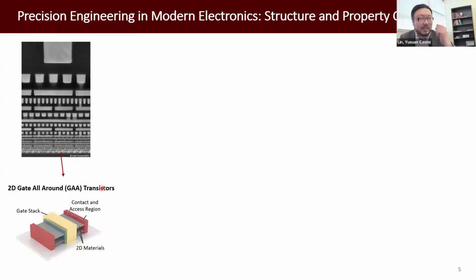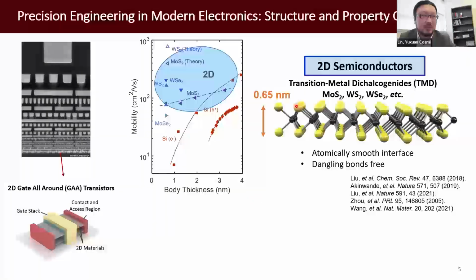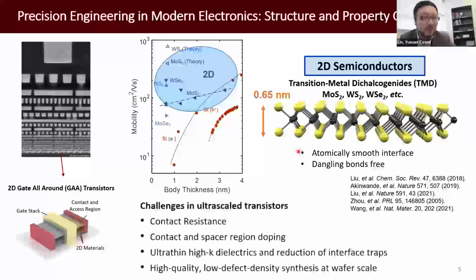The first one is about this ultra-scaled gate-all-around transistor. As I mentioned earlier, because they are ultra thin and a natural two-dimensional crystal, the surfaces are atomically smooth, with no dangling bonds. So when we scale down the thickness of the transistor to below 1 nanometer, there's a benefit in terms of mobility. If we compare it to conventional 3D bulk semiconductors, the mobility would degrade very significantly at that extreme thickness. At the same time, there are a lot of challenges, material or interface related, in order to really realize those ultra-scaled transistors with 2D materials.